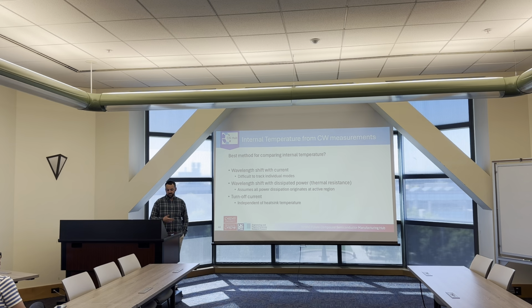You can look at the wavelength shift as a function of dissipated power, so essentially calculate the thermal resistance, multiply that by your dissipated power. But it relies on some assumptions, and also the thermal resistance is something I want to compare between them, so I wanted something separate. So actually you can look at the turn-off current, the current at which the power rolls back down to zero. And there's an important fact about it, that it's independent of heatsink temperature, so that temperature is the same as you vary the heatsink temperature.